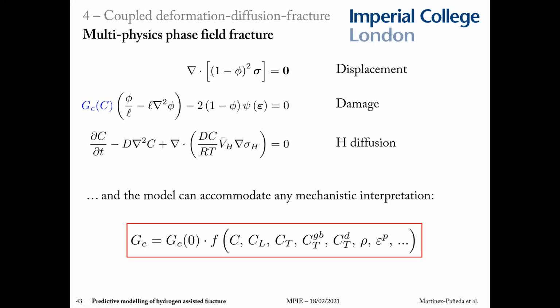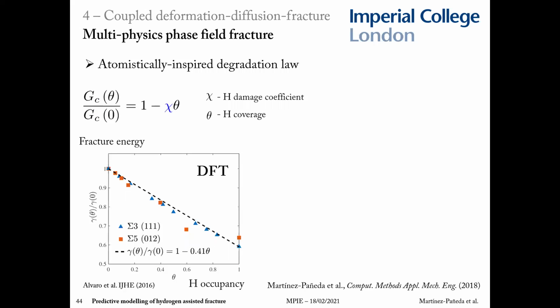It could be the lattice hydrogen concentration, it could be the total hydrogen concentration, it could be the hydrogen trapped in grain boundaries, it could be the dislocation density, any macroscopic or microscopic parameter that you think is involved in the fracture process. And of course, one can also come up with empirical laws by fitting experiments.